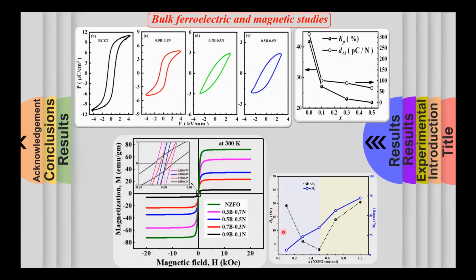As far as the magnetic coercive field is concerned, initially there is a decrease, and a minimum is reached for the 50-50 composite, which means the composite which has 50 weight percentage of the piezoelectric phase and 50 weight percentage of the nickel zinc ferrite phase. Beyond this concentration, the magnetic coercive field value again increases, which is basically due to the requirement of higher energy to switch the larger volume fraction of the available magnetic domains.